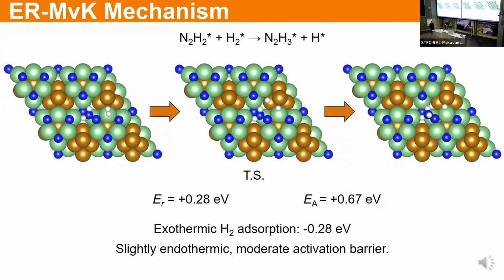As we saw from the mechanism that I've computed for the iron molybdenum nitride system, the initial hydrazine lattice formation and subsequent hydrogenation happens quite easily, it's quite facile, whereas hydrogenation of the second nitrogen atom is a bit more challenging because it sort of resembles lattice nitrogen. So I suspect that's something we would also see for formation of hydrazine. I think from the experimental evidence, this isn't something that's observed, but again, it's a good question and something we could investigate in more detail. Thanks, Andy, good question.